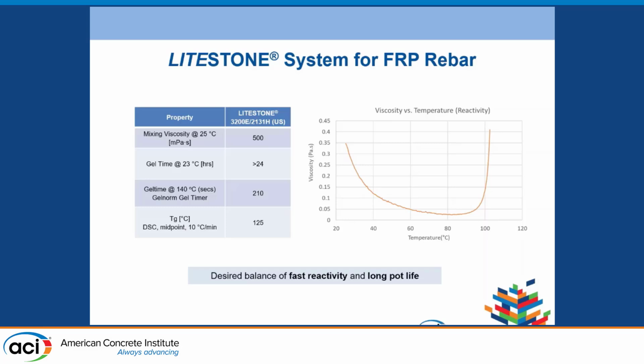When the viscosity is too high, the impregnation is slow. It takes time to wet the fiber. But when the viscosity is too low, it is like water, and the fiber cannot take enough resin. So when cured, you have a lot of dry fiber. So this viscosity is in the right range. And the gel time is over 24 hours, so it doesn't gel fast.